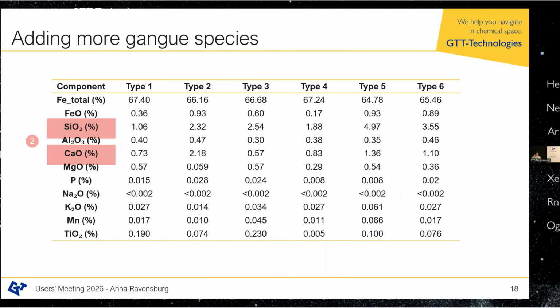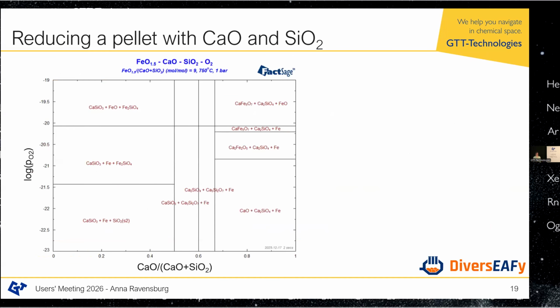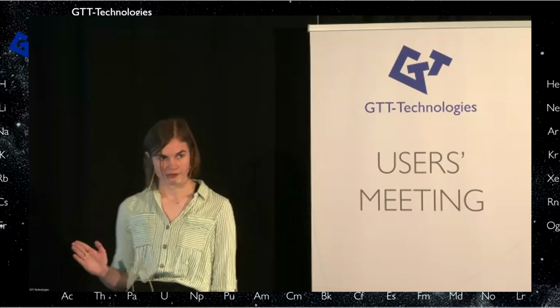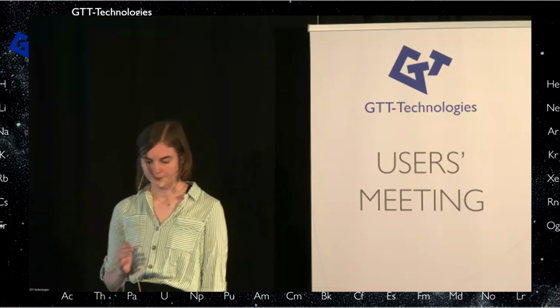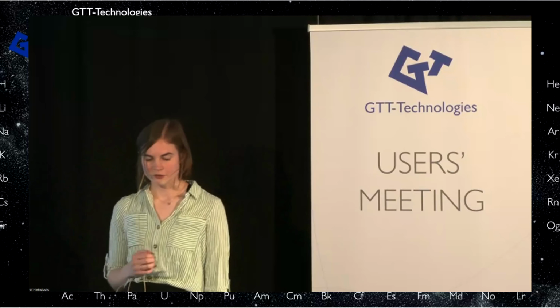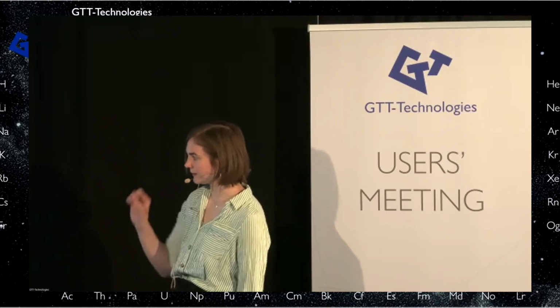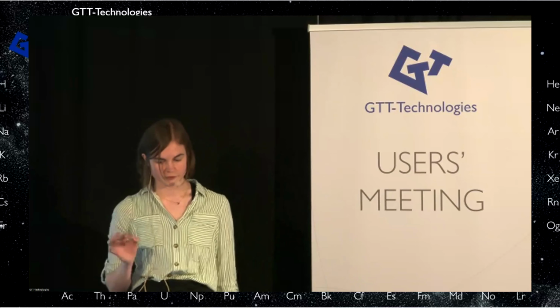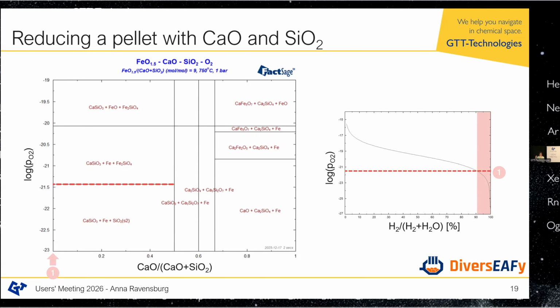Okay, now it becomes more complex. I want to add a new element, a new molecule. So let's go to SiO2 plus CaO. Of course, as GTT, we start with a phase diagram. So on the left side of this phase diagram, you have pure SiO2. On the right side, you have pure CaO, and then the mixture in between. So with the first part that I just showed you, we would be on the left side. And again, here you see this value of minus 21.4, which is exactly the region where we can reach 100% iron. Above this, iron is in Fe2SiO4, and we cannot have full metallization.